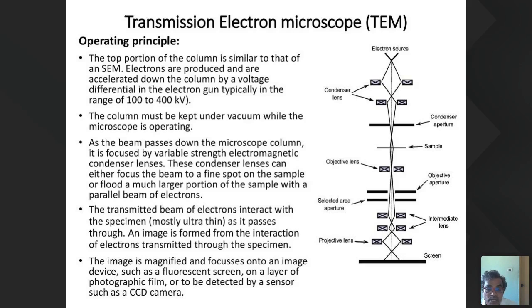As the beam passes down the microscope column, it is focused by variable strength electromagnetic condenser lenses. These condenser lenses can either focus the beam to a fine spot on the sample or flood a much larger portion of the sample with a parallel beam of electrons. The transmitted beam of electrons interacts with the specimen, which is ultra thin. That means your sample must be ultra thin, like a foil or a wafer. As it passes through, an image is formed from the interaction of electrons transmitted through the specimen. The image is magnified and focused onto an imaging device such as a fluorescent screen, a layer of photographic film, or can be obtained through a CCD camera.